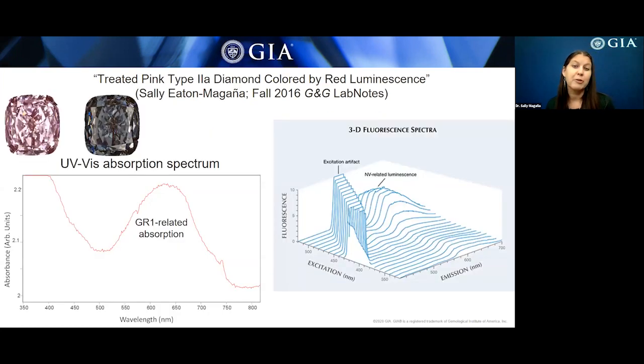This slide shows more detail about the color shift with the diamond under incandescent illumination. The most prominent feature was the GR1 peak in its absorption spectrum, and that creates a purplish gray coloration. This is comparable to the blue color that's generated in many irradiated type 2A diamonds. In daylight equivalent illumination, the emission from the nitrogen vacancy centers was superimposed on the absorption spectrum, and it overwhelms that GR1 contribution in daylight. And so the net effect is that we see a pinkish diamond.